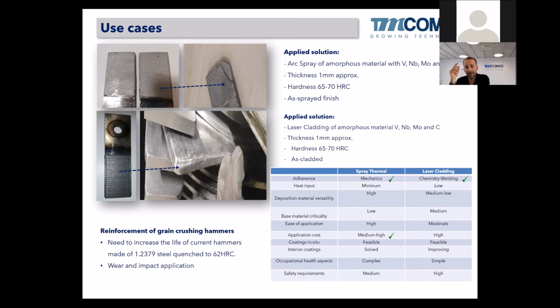Okay, we applied by arc spray a wire-fed material. So we applied by arc spray an amorphous material with vanadium, niobium, molybdenum carbides, and so on. A very hard one, a thickness of about 1 millimeter. So the hardness was about 700 Vickers, which can be 70 Rockwell C.